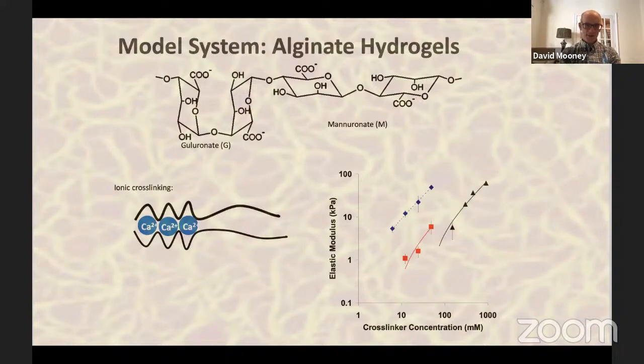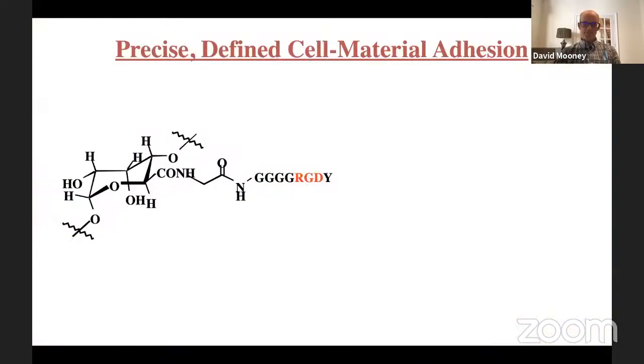And actually the background image that you're seeing here is an AFM image of one of these alginate hydrogels. So you can see the individual polymer strands. They kind of look like pieces of spaghetti. And then you have the spaces in between, which are in the nanoscale. The mesh size in these gels is about 3 to 5 nanometers in size. And so the cells are immobilized and encapsulated within this gel.